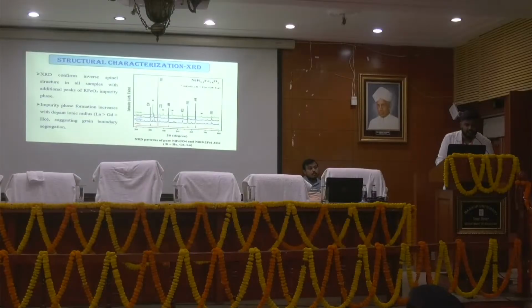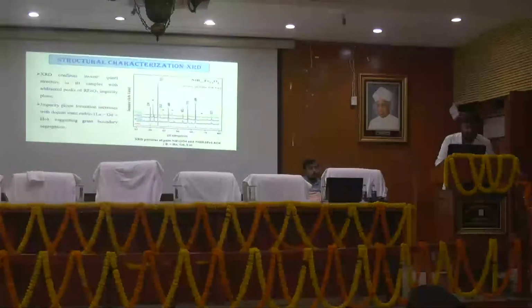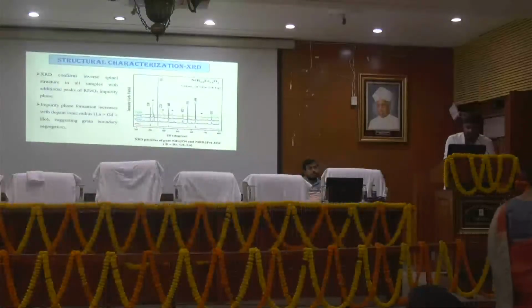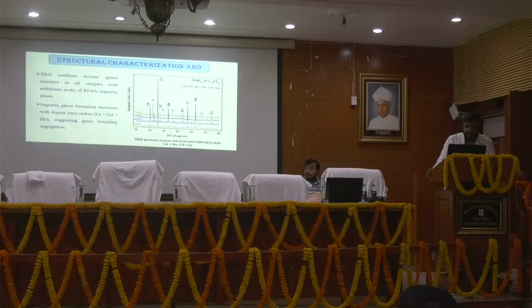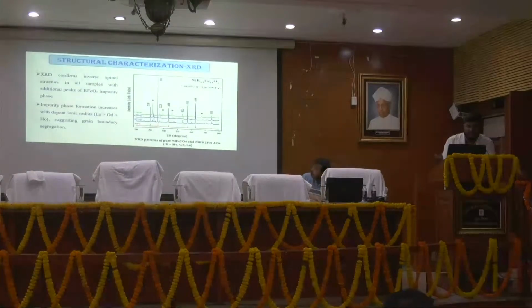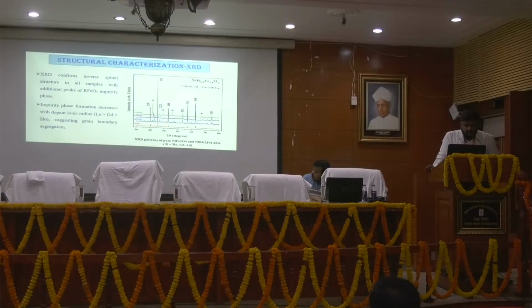This is the XRD of my samples, and this confirms the inverse spinel structure in all samples with additional phases of rare earth impurity. As you can see, I have made the star or asterisk marks there for the additional or secondary phase that has appeared in my samples. Impurity phase formation increases with the dopant, just like we have selected the dopants with their ionic radius, and here lanthanum has the maximum ionic radius. That's why it created the secondary phase.